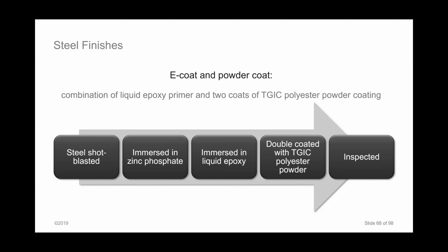Following that, a double coat of TGIC polyester powder is applied, 1 coat of color, and 1 clear coating for a final finish that is 8 to 12 mils thick. Finally, all materials are inspected to meet 100% coating, proper cure, film thickness, and impact resistance. In highly corrosive environments such as coastal areas, a hot-dipped zinc galvanizing prior to applying a finish coat is recommended. This may produce a slightly rougher finish once coated, but will provide added protection against corrosion.